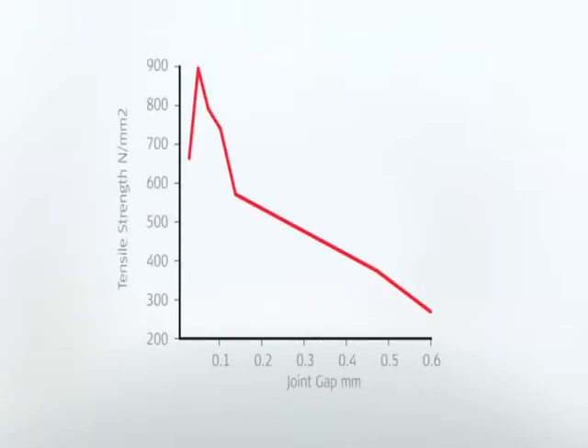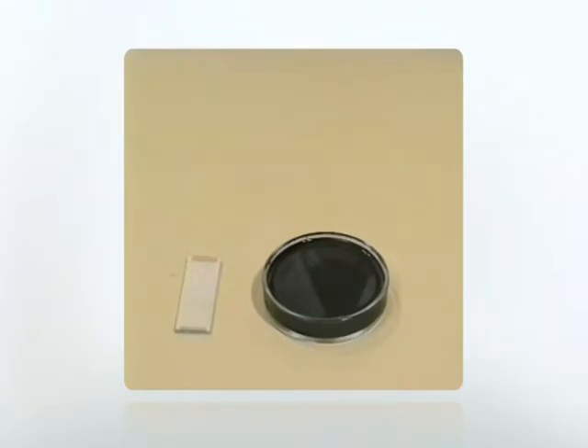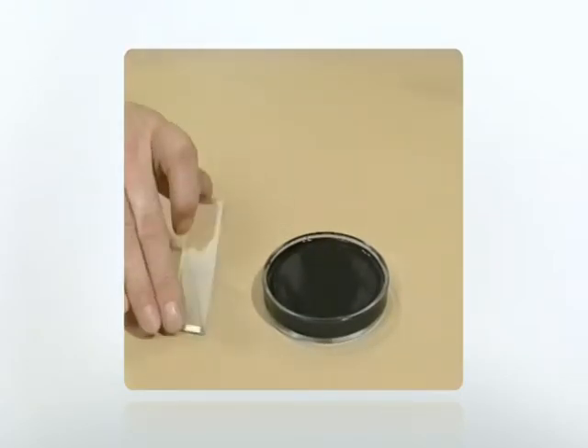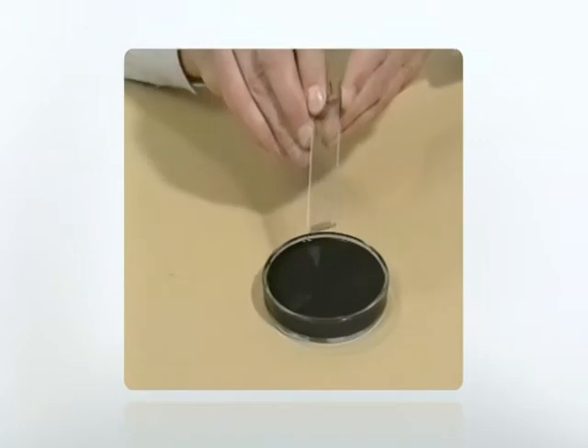But what exactly does close mean? This graph shows how the strength of a brazed joint varies with the clearance. It's based on joints made in stainless steel using Johnson Matthey Easy-Flow brazing alloy. If the gap is ideal, say 0.05 millimeters, the peak strength is about 900 newtons per square millimeter. Even when the gap widens to 0.125, the joint will not fail at less than 600 newtons. These strengths are far in excess of the requirements for almost any brazed assembly.